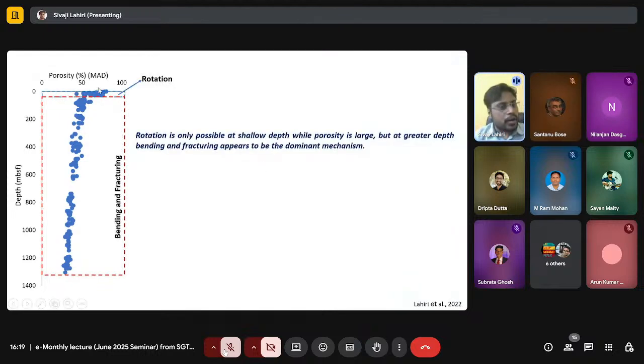So at the shallow depth from seafloor to 30 meter, you observe rotation as the dominant deformation mechanism. However, at greater depth from 30 meter to 1300 meter, we observe bending and fracturing as the dominant deformation mechanism. So there is a transition in deformation mechanism occurring at around 30 meter depth. So the question arises, why is there a transition in deformation mechanism occurring at around 30 meter depth? The answer to this question is actually a space problem.